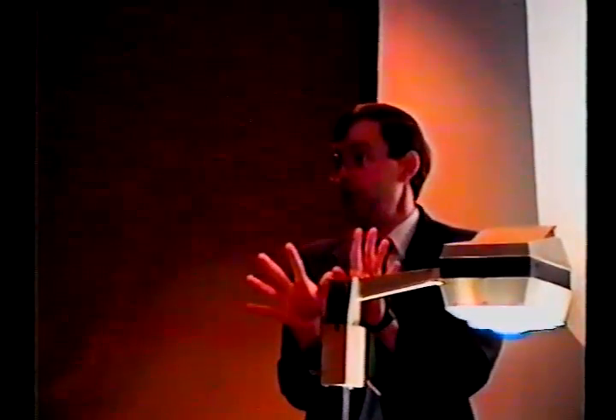So I mean by single domain, when the particles are extremely small, those are called super paramagnetic particles. And what we've done is fit this with a Hamiltonian that is indicative of super paramagnetic particles. That's pretty good for room temperature. I'll show you there are problems. I'll show you some of the lower temperature data.